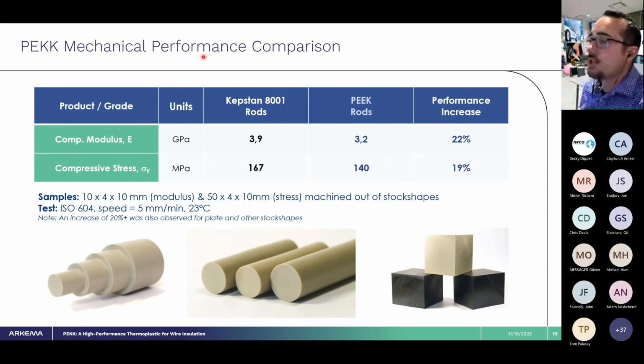This is going to be the compressive strength and modulus of PEKK, same thing with machine stock shapes, tested against both PEKK and PEEK rods. We're going to see a similar trend here, about a 20% or so improvement over PEEK, and that's at room temperature.